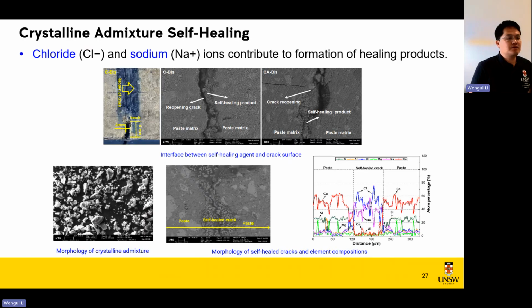Let's look at the effect of chloride solution on the self-healing performance. So firstly, we found the chloride ions changed the mineralogy of the self-healing products and subsequently improved the self-healing performance. At the same time, based on the element composition distribution across the self-healing cracks, actually the chloride solution and sodium solution contribute to the formation of self-healing products.